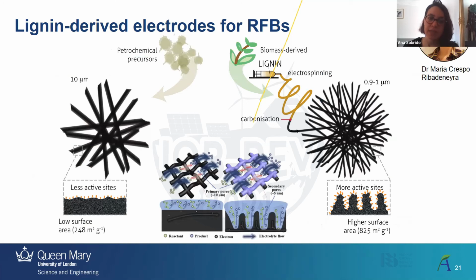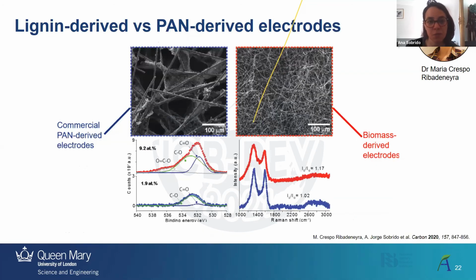So what we have done, what Maria mostly has done, is to develop our lignin biomass-derived carbon electrospun fibers to replace the carbon felts. As you can see, we can produce smaller diameter fibers and higher surface area mats, with many more active sites that essentially enable more electrolyte and active species to be in contact with the electrode as they flow. We've done some research on this, and here I'm going to show you some of the results.